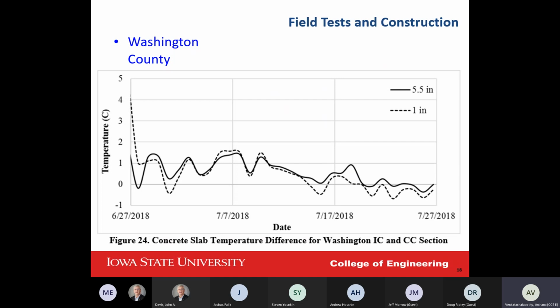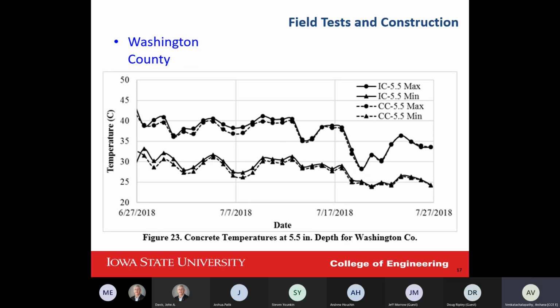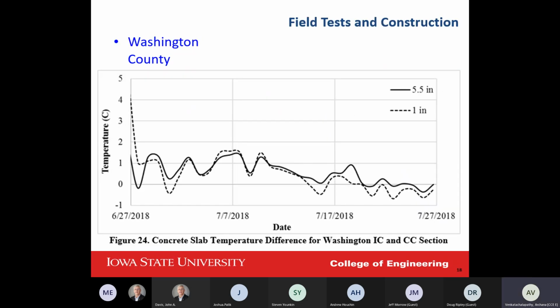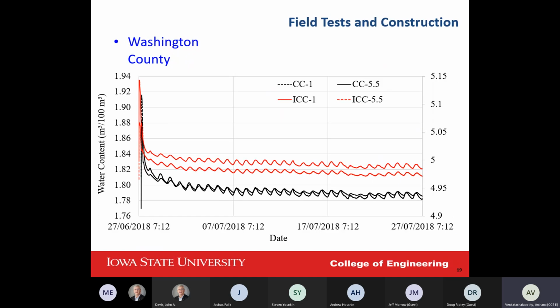As you can see, the solid line is the difference of temperature at the 5.5 inch depth of the slab, and the dashed line is the one on the surface. The temperature difference was between 1 and 2 degrees centigrade, and then after 28 days, it gets closer to 0. This is a different perspective of the previous slide. I just measured these differences and plotted them. In the beginning, it clearly shows we have 1 to 2 degrees centigrade of difference in temperature, and then after 28 days, we're getting closer to 0, which means the hydration is getting closer.